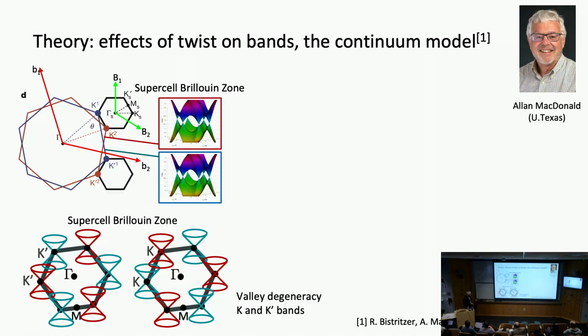And if you put those pictures together, you realize that in each supercell Brillouin zone, in each one of these black hexagons from the Moiré pattern, you would have a Dirac cone from the red layer and a Dirac cone from the blue layer. So you have 2 sets of Dirac cones in each corner of the supercell Moiré Brillouin zone. This is called valley degeneracy, a blue and a red Dirac cone at each corner, and those are labeled as K and K prime bands relative to the original graphene layer. So this is for 2 individual layers that are on top of each other with a relative twist, but not talking to each other, unrelated, not interacting and communicating.